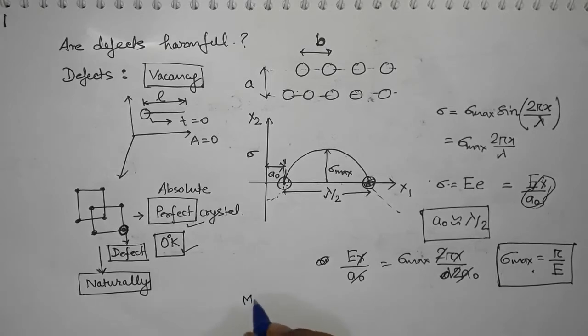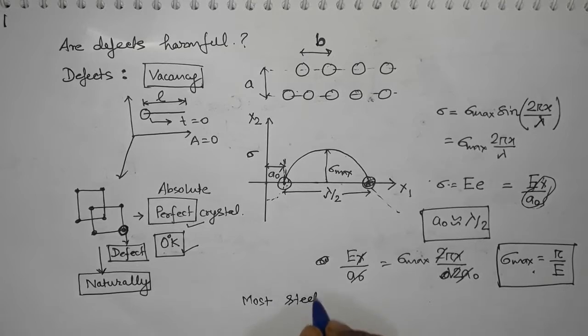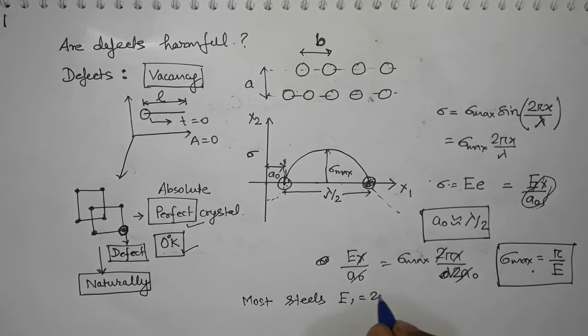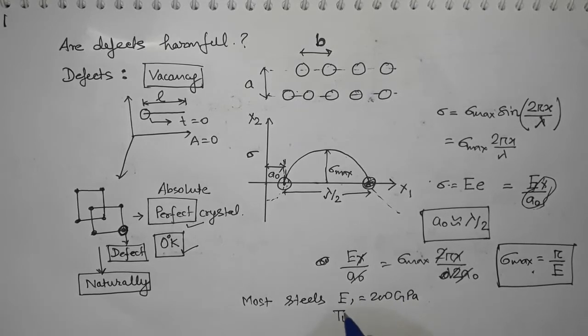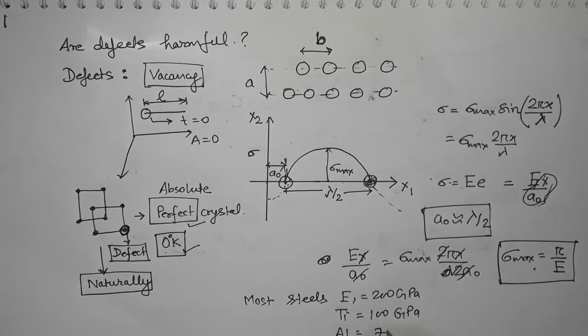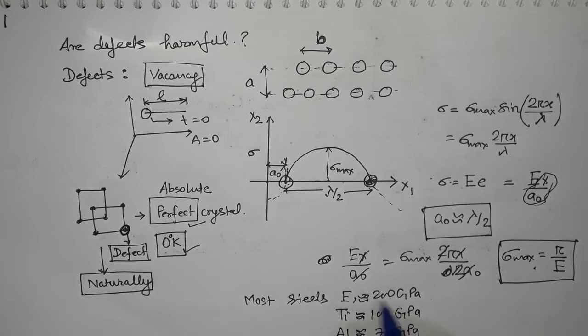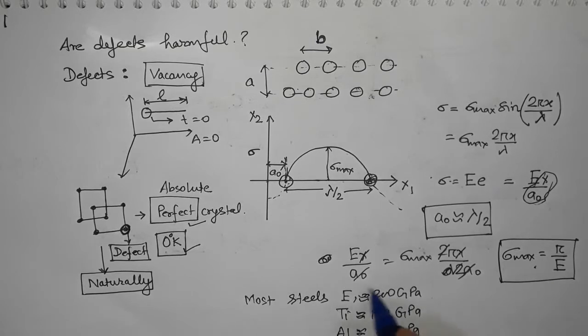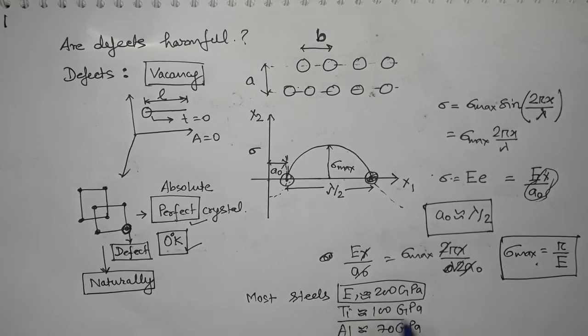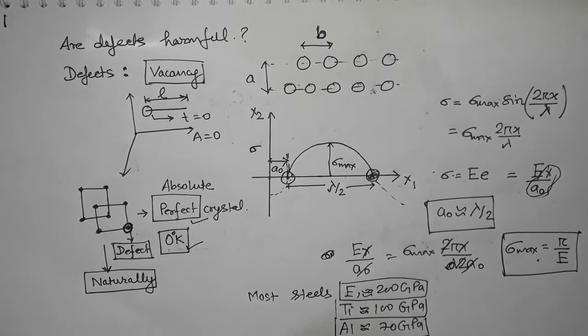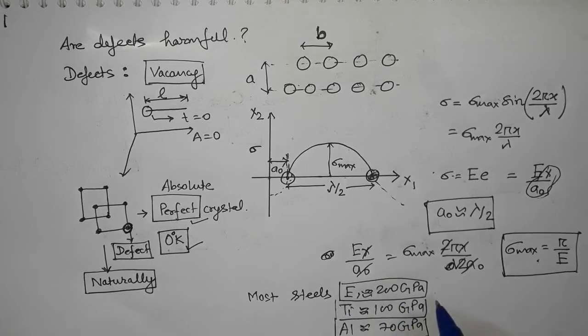And for most of the materials, especially steels, the elastic modulus is in the range of 200 gigapascal. For titanium alloys, it is in the range of 100 gigapascal. For aluminum, it is 70 gigapascal, close to that. Okay, so there can be a change of 2 gigapascal or 1 gigapascal, which will make it 201 gigapascal, 202, 205, sometimes 210. So in this range steel falls, in this range titanium elastic modulus, and in this range aluminum and their alloys. So let us put 200, which is the highest.